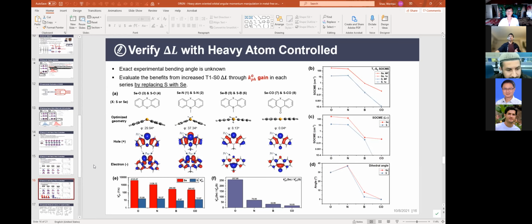It turns out that there is indeed a certain amount of charge transfer from the electron-rich selenium or sulfur to the electron-deficient boron, even if they are within the same molecular structure and so close, which leads to this material having a very small singlet-triplet gap. So it does have certain thermally assisted delayed fluorescence property: at room temperature or a little bit higher temperature, the triplet, once it's been populated, can populate back to the singlet state of this material and emit delayed fluorescence. And we saw that in this material.